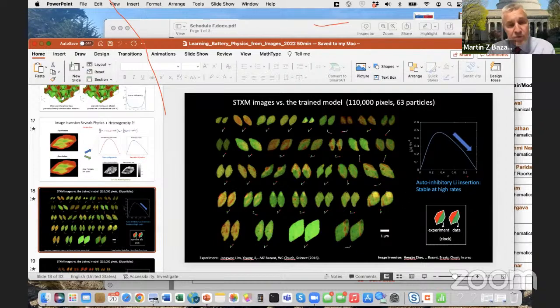But what we've also shown is if you take away some of this data and you say, let's not even fit the surface reaction rate, let's just try to fit the thermodynamic free energy function and just the overall shape of the reaction versus concentration, you can still do pretty well, actually, with much more limited data sets. So there's this trade-off between how well you can do in fitting, how much data you need, and also how much model knowledge you need as well.